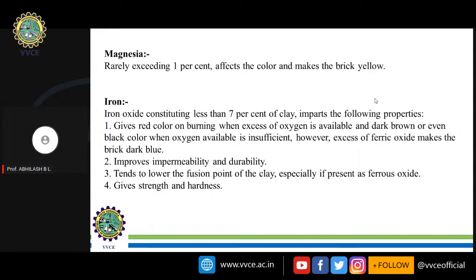Iron oxide gives the coloring property, dark brown, cherry red. It is because of the iron. The strength and durability are obtained from this iron content. Iron oxide constituting less than 7% of a clay imparts the following properties: it gives the red color on burning when excess oxygen is available, and a dark brown or even black color when oxygen is insufficient. However, excess ferric oxide makes the brick dark blue and more brittle, so it will break easily. It improves impermeability and durability. The porosity will be less if iron content is present in the brick. It tends to lower the fusion point of the clay, especially if present as ferrous oxide, and gives strength and hardness to a brick.